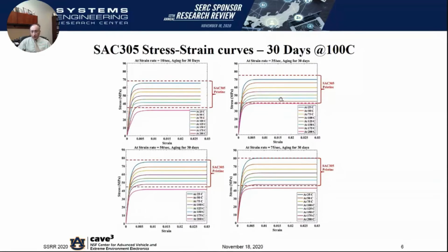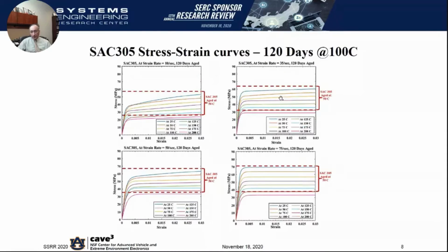And so if I was to go through and flip again, you can actually see as I go from 30 to 60 to 120, the curves successively migrate downwards, which basically indicates that the ultimate tensile strength is evolving, the effective modulus is evolving, and the material behavior is continuously changing as well. And the brackets here indicate the effect of the sustained storage temperature. These curves are at 100 degrees centigrade, but if they were at 50, that's where the curves are. And that's data that's been taken earlier on in the study.